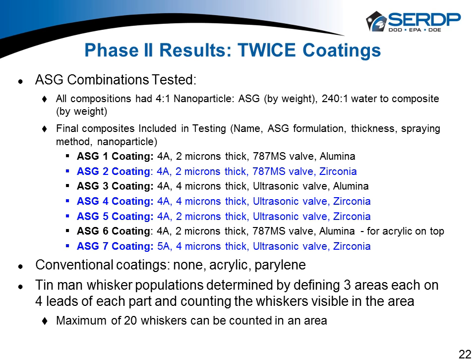What we also have built into the program is we knew that Nate had seen some other particles that we might want to try. And so we knew alumina was really good, but we said, let's try zirconia. We had some really good results with zirconia on flat samples, not on test boards, but just on glass slides. At the same time, Plasma Ruggedized Solutions and Nate found that there was a better application head. So we had been using the 787 dispensing valve, and Asymtek came out with an ultrasonic valve, which gave much better application speed and time.